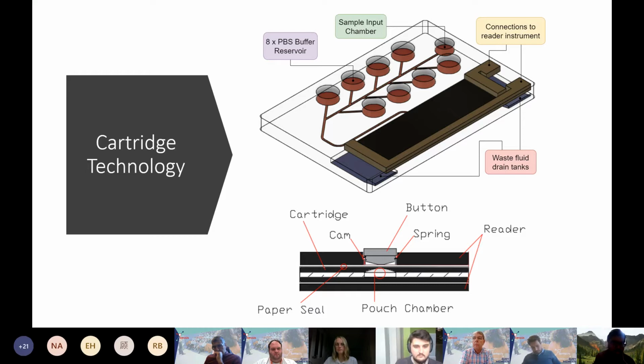And using our aptamers, which are made with LDNA for enhanced nuclease resistance, we found papers that suggest that aptamers are able to survive in saliva samples for up to 45 minutes. So that's why we've limited our test to under 5 minutes. So that way we can use our cartridge up to 8 times. So 5 times 8. And the regeneration process is very simple.